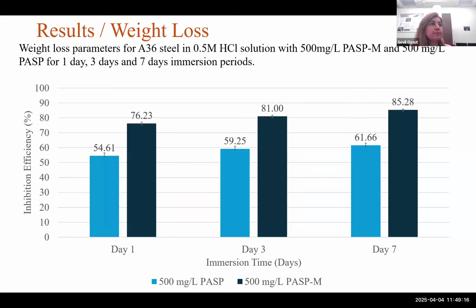And these are the results for that highest concentration for both polyaspartic acid and the methionine functionalized polyaspartic acid, just to show whether the functionalization gives better results or not. The blue one is the polyaspartic acid, and for all the duration times, the methionine functionalized one shows superior, higher inhibition efficiency in terms of decreasing the corrosion rate. So it shows that having good heteroatoms in the structure provides adsorption sites and better corrosion inhibition.